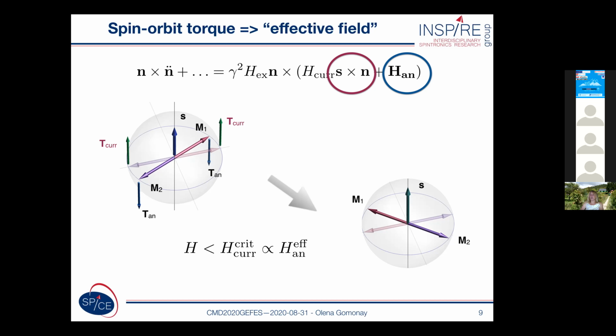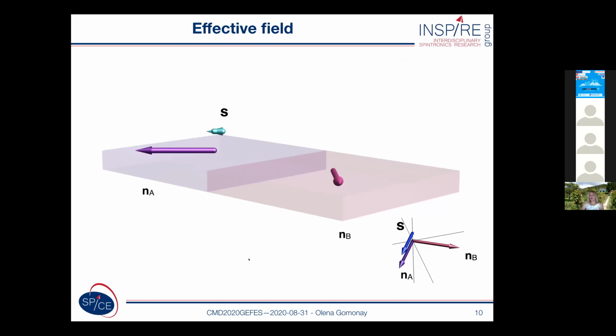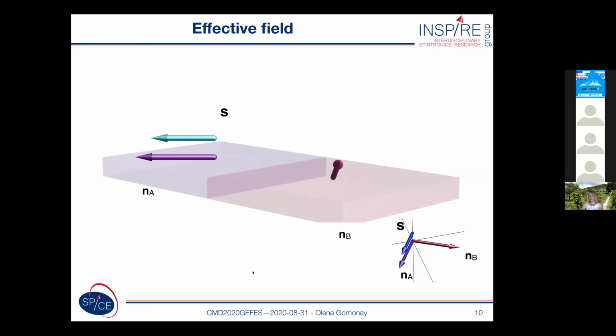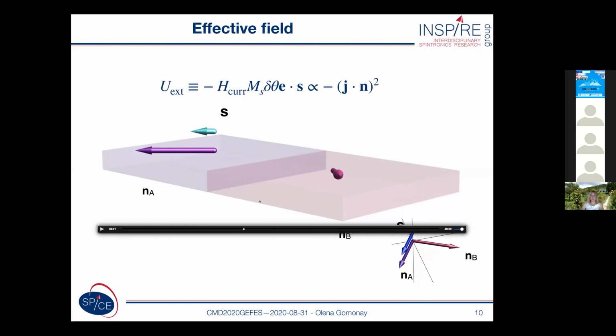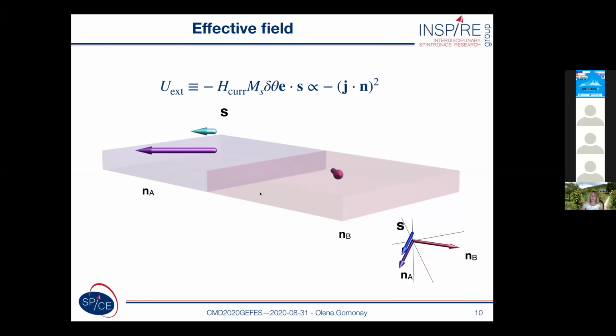To find the potential energy associated with these torques, we consider the system consisting of two orthogonal domains, A and B, with orthogonal directions of the Néel vector. So the movie, which you see now, demonstrates the effect of a spin current on the equilibrium orientation of the Néel vectors. The green arrow shows the orientation of spin, and the length of the arrow is proportional to the current density. So you see that in the domain A, the Néel vector is insensitive to the spin pumping, while in the domain B, equilibrium orientation of the Néel vector changes. This is associated with the energy potential, which can be approximated by the expression which you see above.